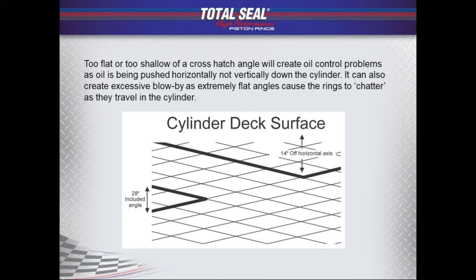Too vertical can create a problem. Typically, most crosshatch angles in a high RPM, short stroke engine, you're going to see somewhere between 30 and 36 degrees included. Most of your general applications, you're probably in the 40 to 45 degrees included. And there are some applications out there that are going to be in the 60 degree range. Some of your Harleys are like that. A lot of your Subarus, just about every factory Subaru cylinder I've ever measured is sitting at about a 60 degree crosshatch angle. That's not to say that they can't use something flatter, but based off what they're doing, they're about 60 degrees right out of the box. So again, a handy little tool to double check your crosshatch angles.